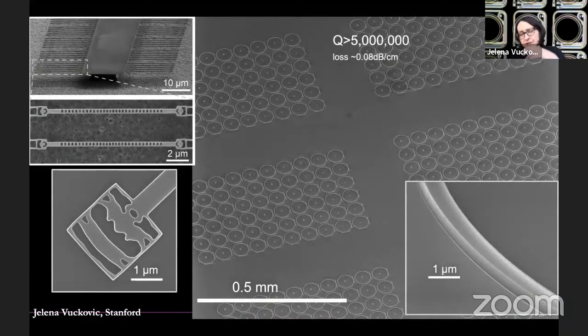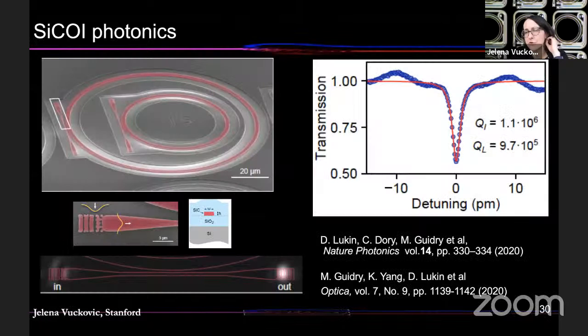And as a result of this very high quality silicon carbide, we're now able to measure really high Q factors, actually better than in silicon on insulator. We have Q factors of 5 million, very low loss. This loss is comparable to silicon nitride. We can combine it with inverse design, and there are a lot of structures that are shown here. You can see some of the older measurements with Q of 1 million. Again, you see inverse design couplers. We use them routinely for this.